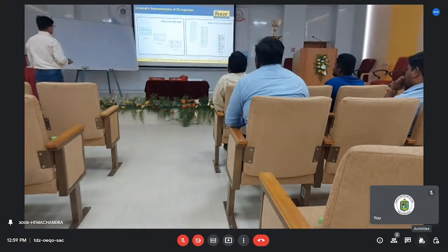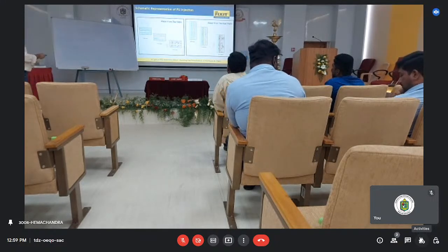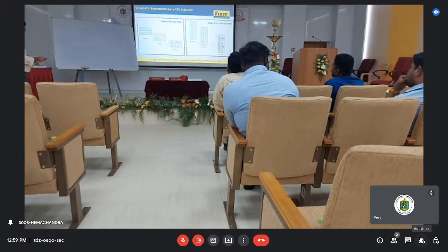Now, what is happening, as I told you till now? Suppose water is coming from the top surface and moving like this. As we put in the PU foam injection, we go up to this much and then inject it. Then all the areas, this brown side, you can see, are getting foam. Then it is followed by plain injection to fill the other areas.